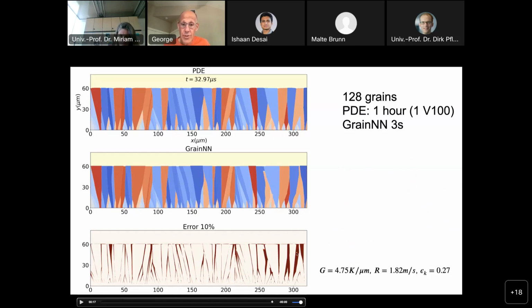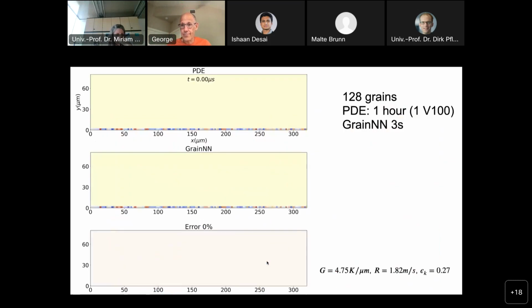And you can see the point-wise errors actually can be quite significant, right? So for example, you can see here the structure in the phase field is somehow different from the neural network. But overall, in the eyeball norm at least, the structure is the same, and here you can see the precise misclassification errors. Again, when you see dark, that means the pixel is classified to the wrong grain. And the PDE solver took about 1 hour, whereas the grain NN inference took just 3 seconds.